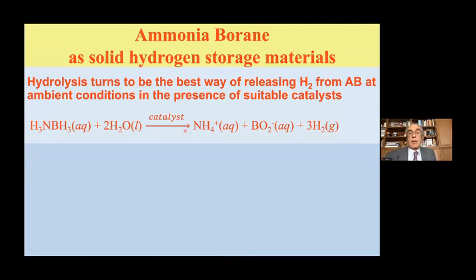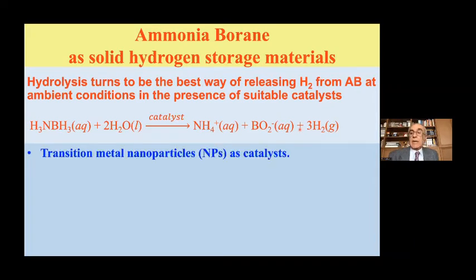It has a very high hydrogen content, almost 20%, and it is stable in solid state and also in solution. And it can release hydrogen from its hydrolysis. Here you can see the reaction. It releases 3 equivalents of hydrogen per mole of ammonia borane from that hydrolysis. But that hydrolysis can occur only in the presence of a catalyst. Without a catalyst, it is stable.